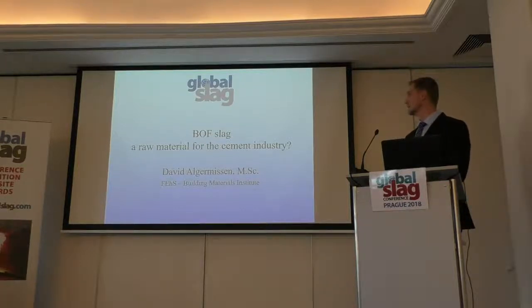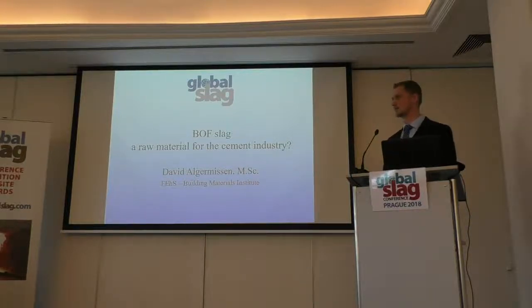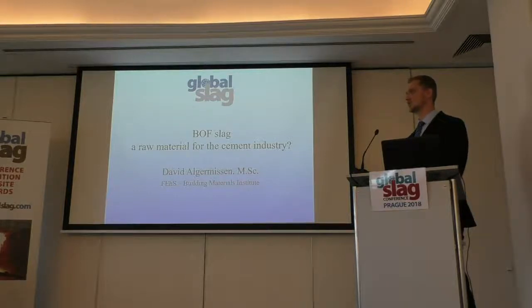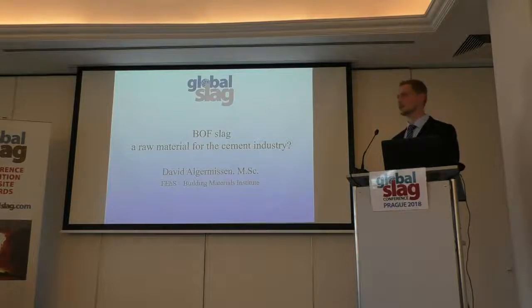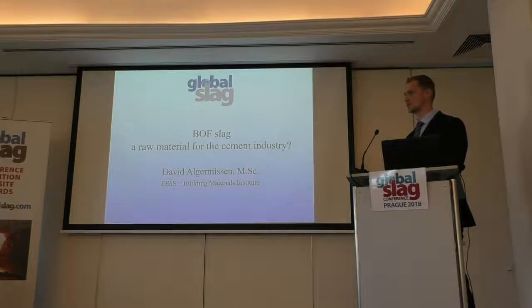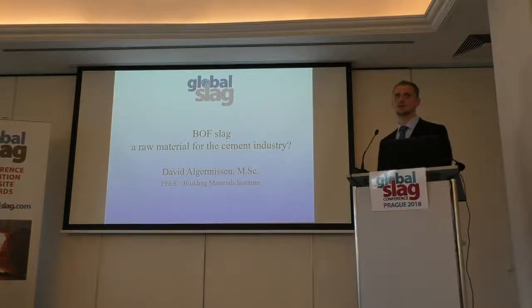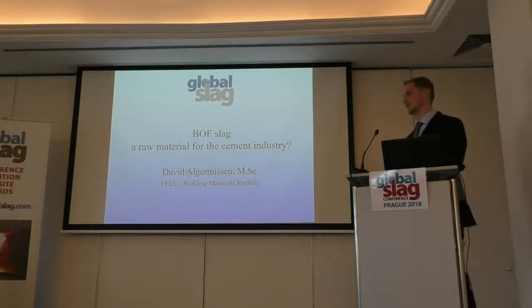The advantage for BOF slag is that it comes with a very high calcium oxide content, so it should be an easy way to go to the clinker, but due to the high viscosity we are not able to handle it. And with the EAF slag we have to increase the lime content with lime, and then we got the same problems like you saw here in the videos. So in the EAF project we also looked more to the GBFS way.